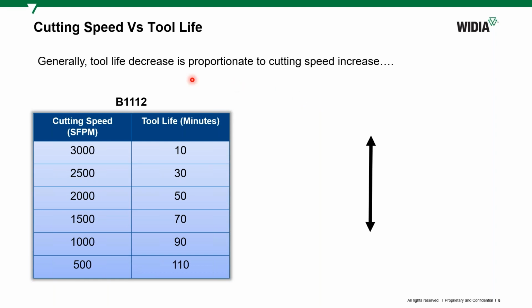Okay, so now we talk about machinability being mostly defined in terms of the cutting speed. Now, what is the role of cutting speed in simple terms? So at a cutting speed of 3000 surface feet per minute, the typical tool life is 10 minutes. And as you reduce the cutting speed and go to 500, which is 1/6 of 3000 SFPM, you can see that the tool life has increased to 110 minutes. That is an increase by 11 times. So even though speed has dropped by 1/6, the tool life has increased by 11 times. So even though there is a relationship between the tool life and the cutting speed, they are not linear.